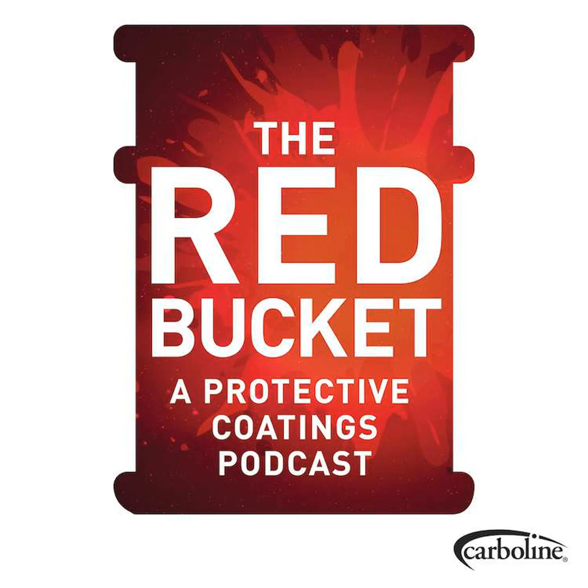And so they are obviously microscopic, atomic level, and you don't have to have the zinc necessarily in contact with metal in that one spot for that galvanic cell to initiate. You need an electrolyte, usually it's water. Salt helps. Sometimes pH, a lower pH can help as well. And if you have those, then you have a vehicle for those electrons to move. So you can have your zinc doodad kind of far away from a spot on the hull and it can still be protected. And so that same concept actually rings true in how we utilize zinc-rich primers.